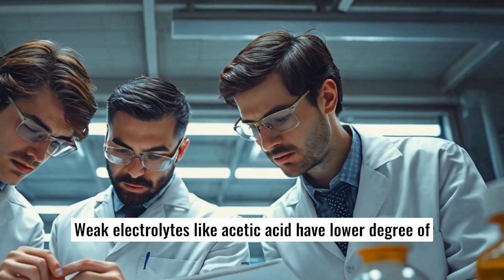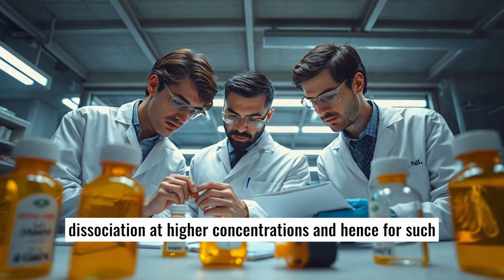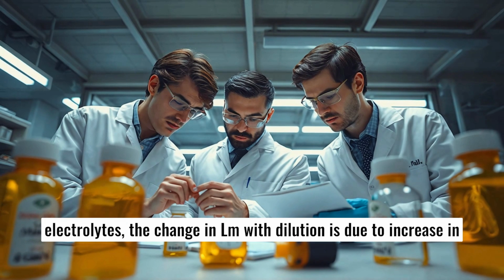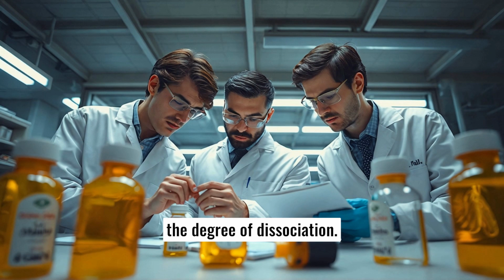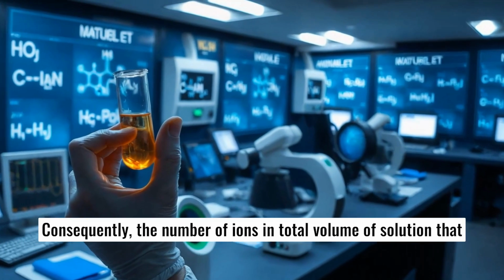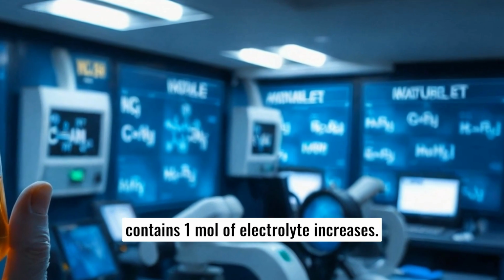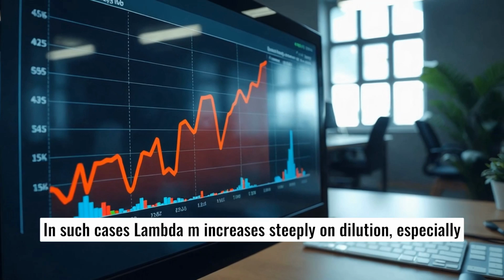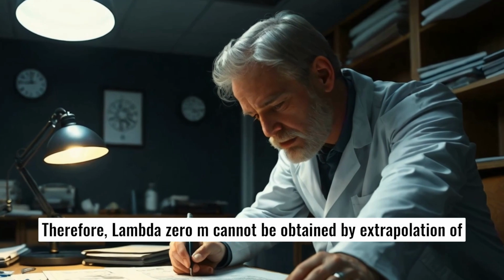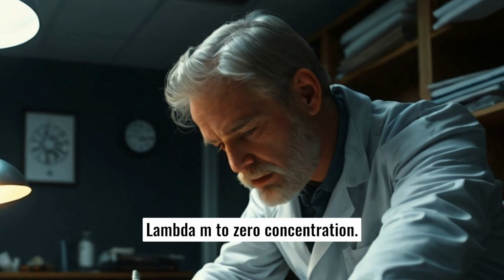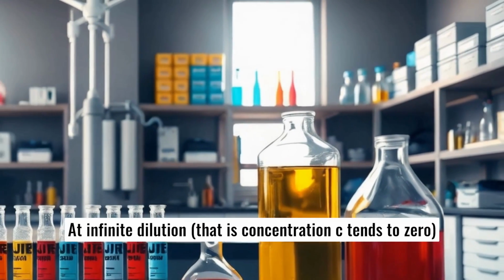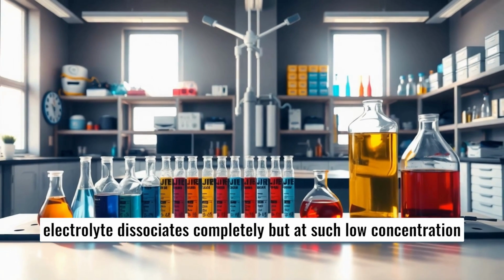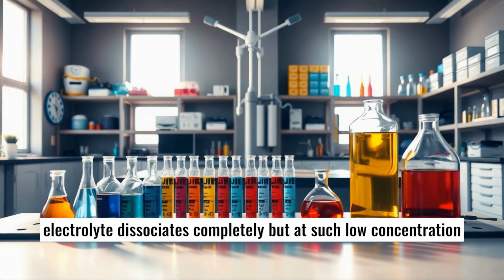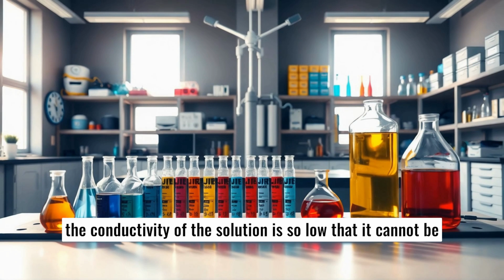Weak electrolytes like acetic acid have lower degree of dissociation at higher concentrations, and hence, for such electrolytes, the change in Λm with dilution is due to increase in the degree of dissociation. Consequently, the number of ions in the total volume of solution that contains 1 mole of electrolyte increases. In such cases, Λm increases steeply on dilution, especially near lower concentrations. Therefore, Λ0m cannot be obtained by extrapolation of Λm to 0 concentration. At infinite dilution, that is concentration C tends to 0, the electrolyte dissociates completely, but at such low concentration, the conductivity of the solution is so low that it cannot be measured accurately.